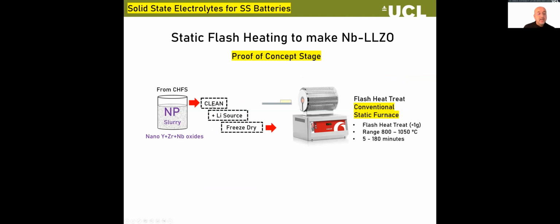We added the lithium, so we cleaned them up, obviously, got rid of any residual ions. We added lithium, we freeze-dried that to distribute the lithium very evenly. And then we basically did a series of flash heat treatment experiments, a range of times and temperatures. So this is our design of experiments. It's a grid of time versus temperature.